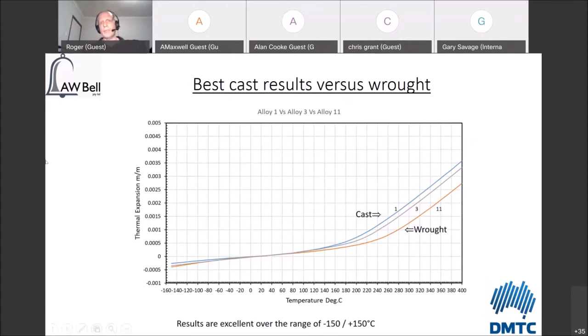So the best cast results are shown here, alloy 1 and alloy 3 versus alloy 11. Alloy 11 was the wrought Boeing specification material, which I had tested together with the cast material. And you can see we actually performed pretty well in comparison. The cast material, alloy 1 and alloy 3, were not bad, especially over the range of minus 150 to plus 150. And alloy 1 actually outperformed the wrought material, because the wrought material dips off more down at these low temperatures than the cast material did.